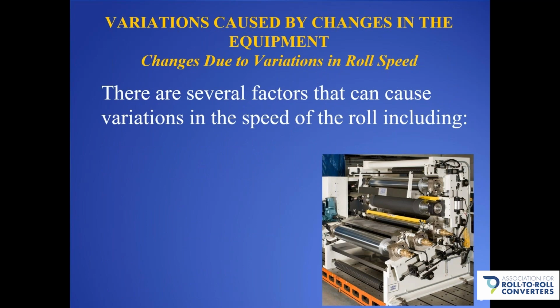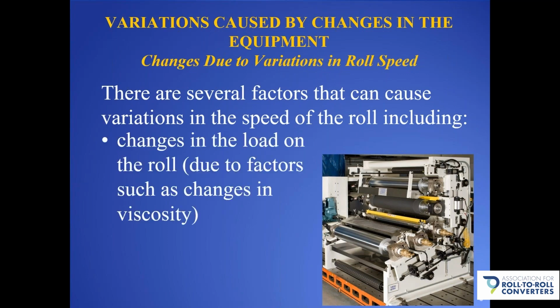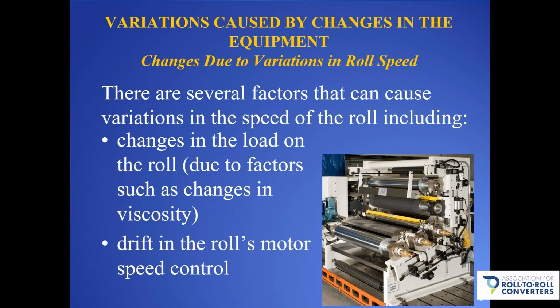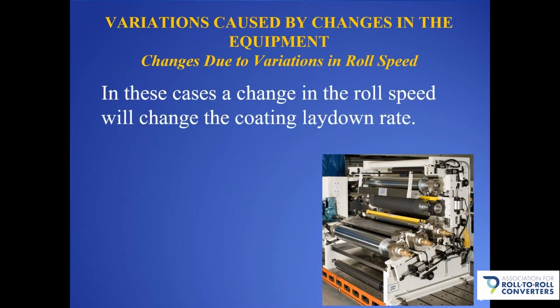Now there are several factors that can cause variations in the speed of the roll, including, and this is very similar to what we talked about for pumps, a change in the load on the roll, in this case due to factors again such as changes in viscosity or maybe changes in gap setting, or a drift in the roll's motor speed control. And in these cases, a change in the roll speed will change the coating laydown rate.